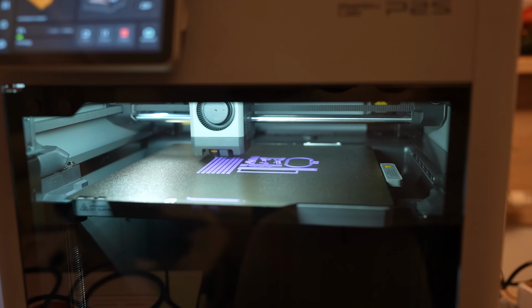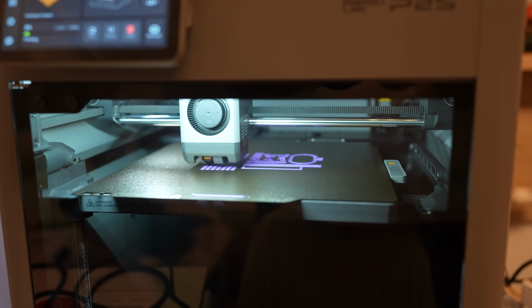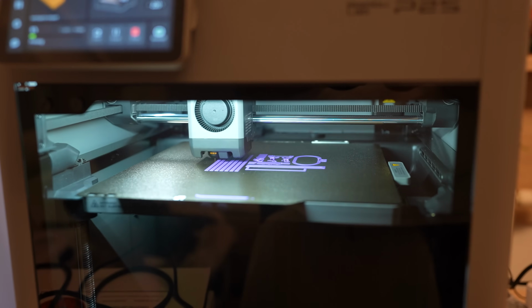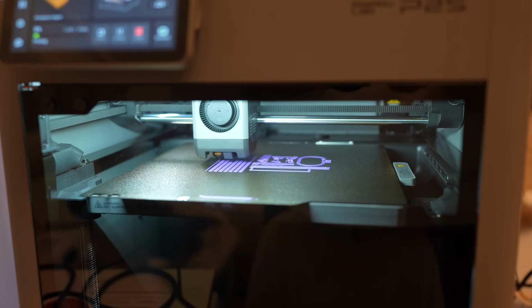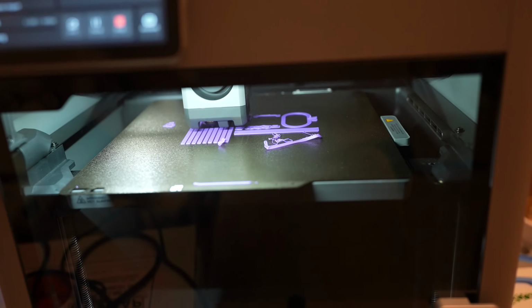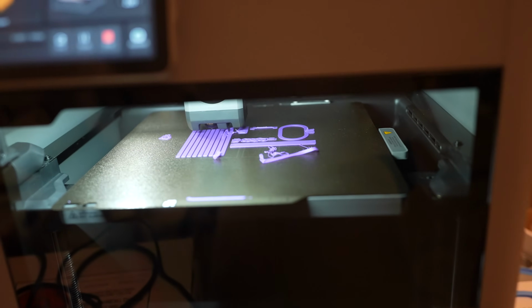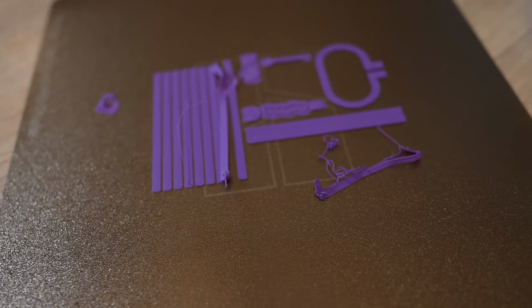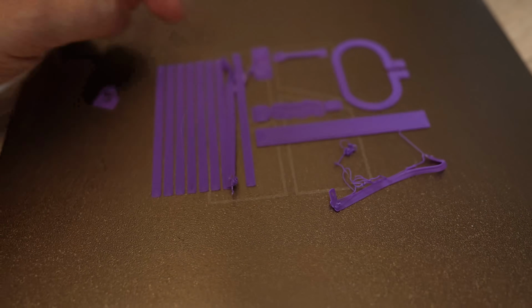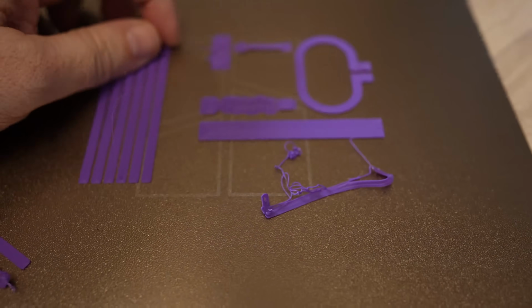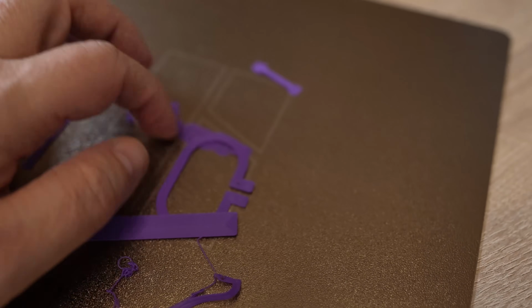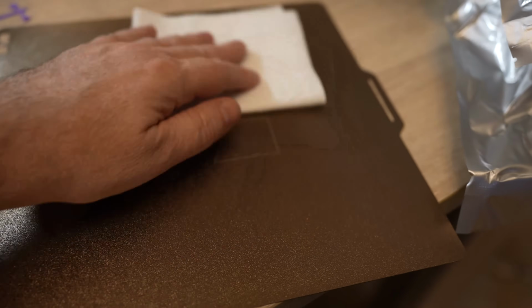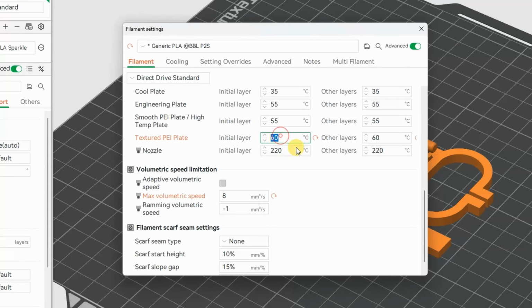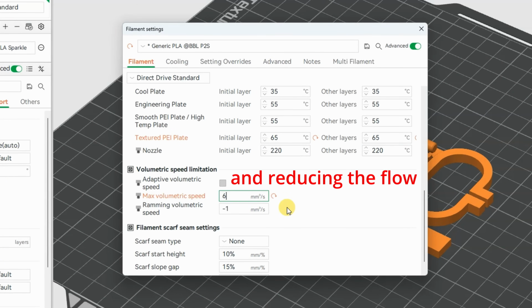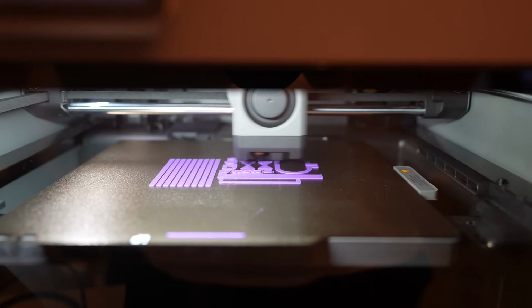I can feel some unpleasant smell. It is not too strong, but definitely this is not like regular PLA, and I have to ventilate the room after the printing. Oh, looks like there are some problems with bed adhesion. Not sure what happened. But yes, adhesion could be better for PLA. I'm cleaning the bed with isopropyl alcohol, and I will increase the bed temperature to 65 degrees Celsius. So far I don't want to use the glue stick. It passed that critical point.